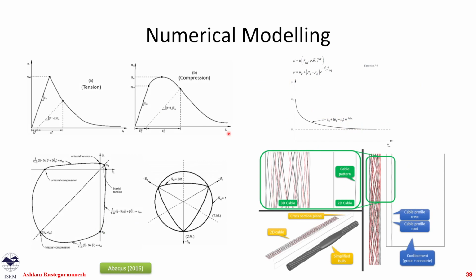So this is our boundary condition. We have roller on the top, roller on the sides, and our axis of symmetry has the roller too. And this is our cable, our annulus, and our concrete here. For constitutive modeling for our concrete and for grout, we use concrete damage plasticity, or CDP in Abaqus, which is a very famous one. We basically give the parameters for the damage, in tension and compression. And in the bottom section, we see the failure load test of that, the CDP model.